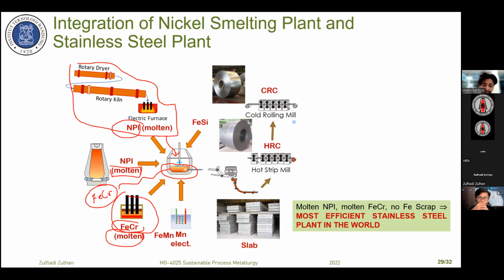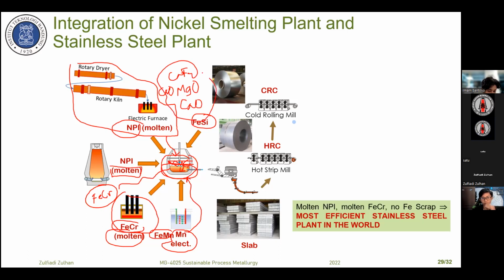And then at the end, after the removal of carbon, we add ferrosilicon and also ferromanganese or electrolytic manganese to adjust the silicon content. Ferrosilicon is added also to reduce the chromium oxide from the slag, to get high recovery of chromium, and also to get the final slag, which is used for desulfurization. We should also reduce the chromium oxide, and then we also add CaO. I informed before that CaO and MgO or dolomite, and CaF2 are added to adjust the slag composition.